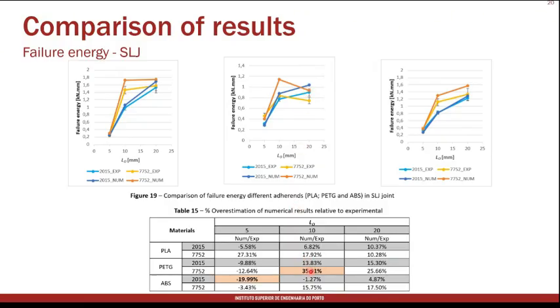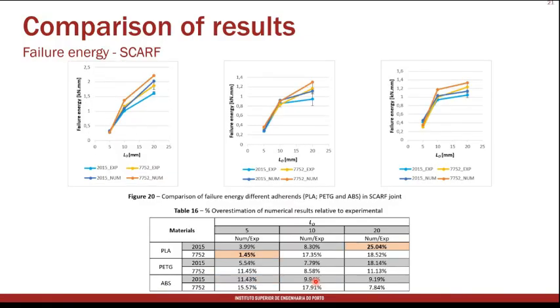Here we also have good correspondence, but there were few cases in which we have deviations up to 30-40%. And this is also a parameter that is more difficult to measure because it involves many variables such as the maximum load, displacement at failure, and it's easier to accumulate error than, for example, in the maximum load itself. The results were closer between experiments and numerical simulations for the scarf joints, and here we have an increase between 5 and 20 millimeters, although bigger between 5 and 10 millimeters.